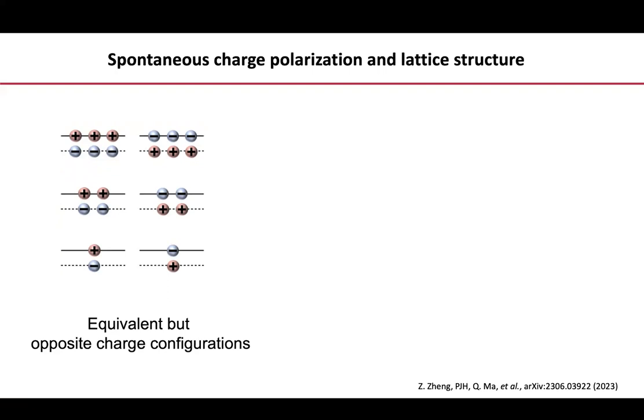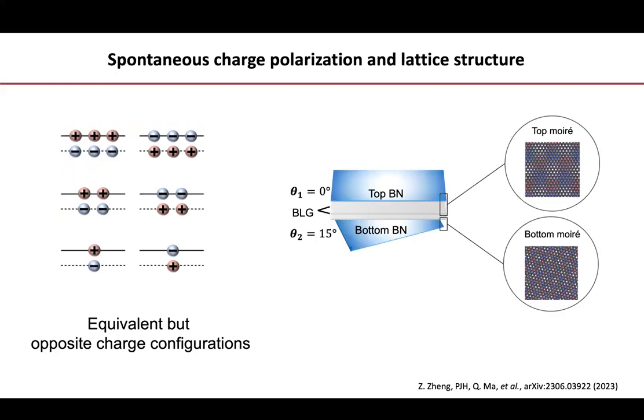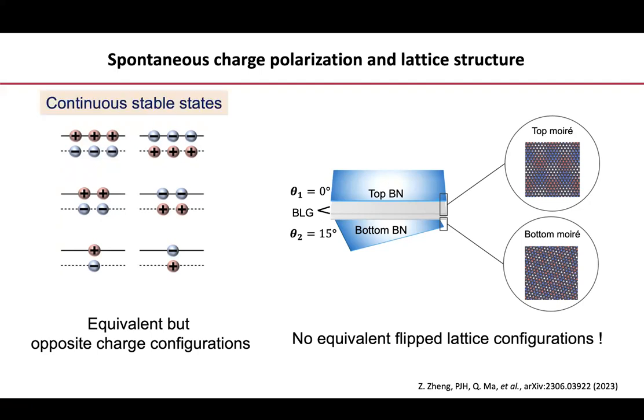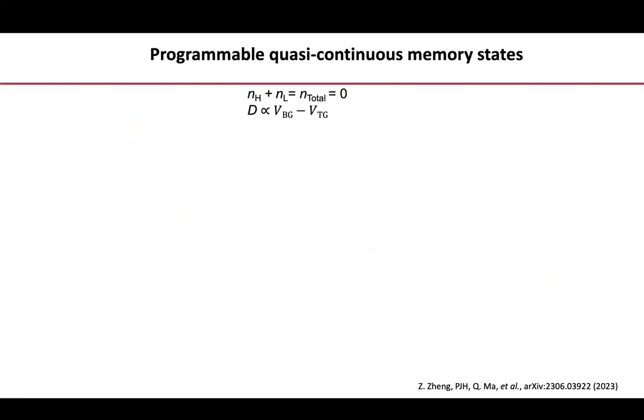So that's just a weak symmetry-breaking field, which is not the responsible symmetry breaking for the ferroelectric action up and down. So these are not equivalent flipped lattice configurations. The lattice remains the same and I flip the entire dipole moment. Because I can do this continuously with this number of excitons, I now have a ferroelectric memory, where I have continuously programmable memory states.